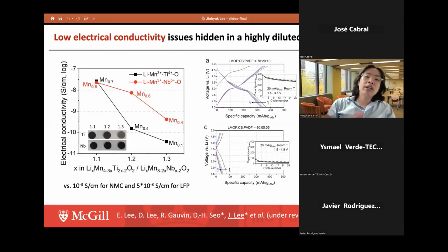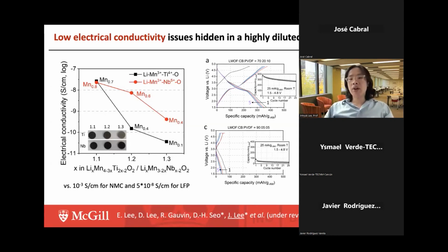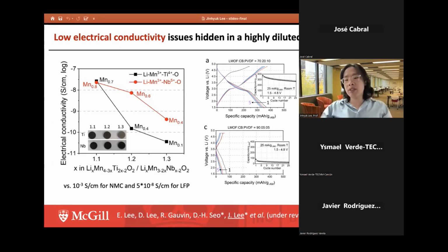And finally, I would like to say that this type of phenomenon is universal for many different types of DRX material, including another type of DRX material. If it's 70-20-10, it cycles well. If it goes to 80-10-10, it performs poorly. And now at 95-5, you basically cannot cycle this material at all. So this is very universal. So this low electrical conductivity becomes a very important problem.